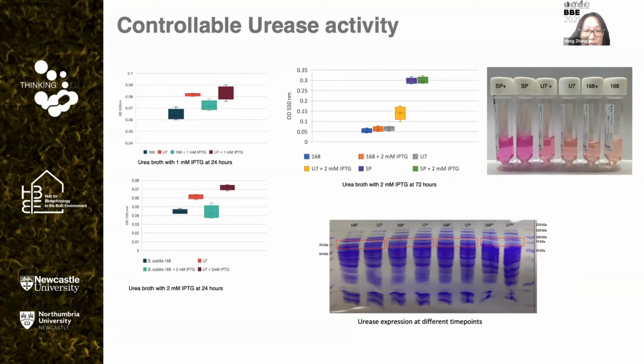However, when we conducted more investigation into expression, we found the recombinant urease is not very stable. If you look at the bottom gel image, you will see the expression of the urease starts to disappear when we harvest the cells after 6 hours of induction. So we decided to integrate those gene clusters into the subtilis genome to produce a stable system. And Jen is in the process of doing those experiments.